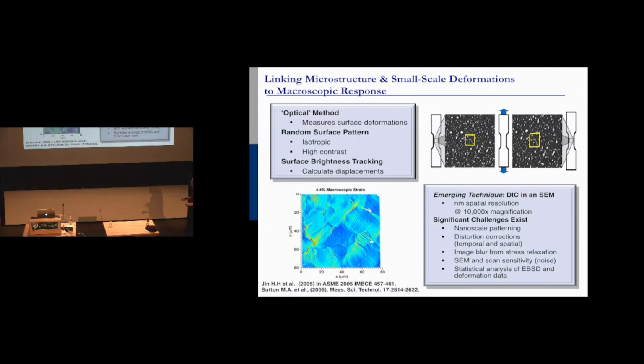We built this off of some ideas and framework fortunately from Helena Jin and Mike Sutton. And so the first thing we had to figure out was, how do you pattern something? We basically wanted the equivalent of dropping like 500,000 strain gauges inside a 10-micron field of view. For reference, if you take a penny and you flip a penny over and you find the Lincoln Monument, and then you go find Abe Lincoln inside that monument, and then you go find his legs, okay?